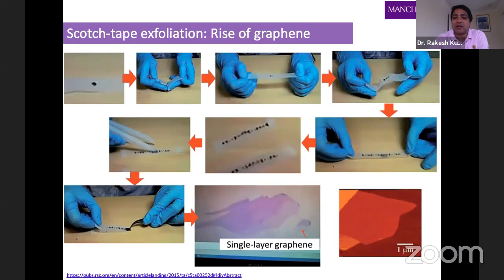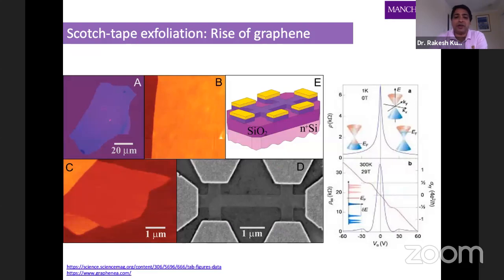It was the simplest experiment. They started by isolating graphene from graphite using scotch tape. If you take a piece of graphite and a scotch tape, you can just keep pressing and peeling it several times until you start finding these layers separated on the scotch tape. Then finally, you take any substrate, whether an insulating substrate or silicon oxide, and you can transfer these single layers of graphene onto that. Then you can inspect it under the microscope or with other microscopy tools in order to look into the single layer, double layer, or multi-layer. And once you have a flake of graphene on a silicon oxide surface, you can make a device in order to extract all the electrical and magnetic superconducting properties.